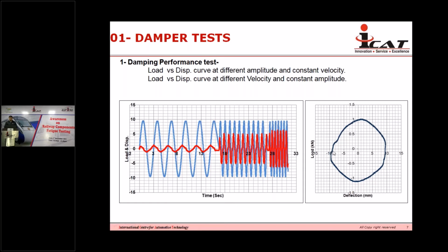Another is we plot the load versus deflection curve of one cycle to understand the behavior of a damper. Generally it makes a square shape, but not completely square, more of a circular shape. So this is the load versus deflection in the case of a damper, but if it is versus velocity, then it is a straight line. These are some characteristics tests we perform before conducting the fatigue test inside our lab. For every damper, we check the performance or characteristics after the fatigue test as well. So we conduct these performance tests both before and after the fatigue test.